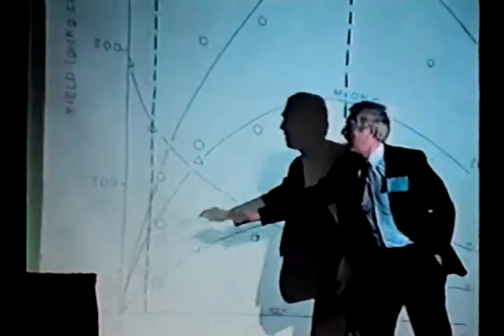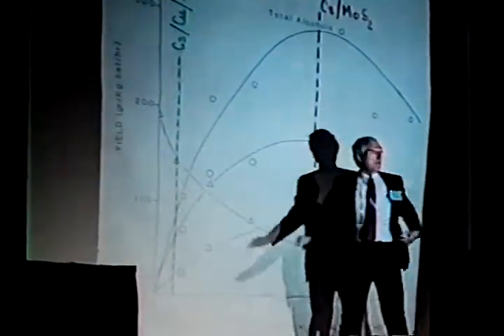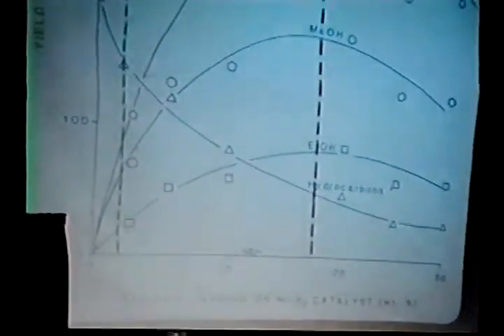The pure molybdenum disulfide is no catalyst for alcohols at all. It is a moderate catalyst for making methane primarily from carbon monoxide and hydrogen. As one dopes this solid more with cesium, which is introduced in this case in the form of cesium formate, we make alcohols, primarily methanol. Then when one overdopes, one makes less methanol. In parallel to the methanol, while hydrocarbon production is suppressed, parallel to methanol production is ethanol production and some higher alcohols.